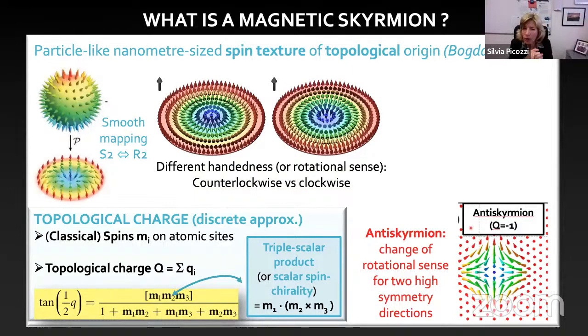So here also we don't have any continuum approach. We have discrete spins, which means that to calculate what characterizes the skyrmion, this topological charge, we basically had to consider the formulation of the topological charge on a discrete lattice, or with discrete spins. And so we basically evaluated on this triangle this triple scalar product, what is called scalar spin chirality. So you see here that it's a scalar product with a cross product of two others.